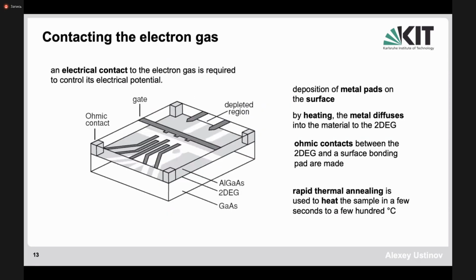And then you make a structure of these gates, such as, for example, shown here. So these are your metallic electrodes. You draw them with the electron beam, and that's where your metallic film is located. And then you also need to make a contact to this two-dimensional electron gas and also to the gates. So the top structures are called gates, and the two-dimensional gas is at some distance below the surface, as I already explained. So in this case, you have to deposit some metallic pads here and then use some moderate heating to make the metal diffuse into the material of the two-dimensional electron gas and form an ohmic contact to the two-dimensional electron gas.